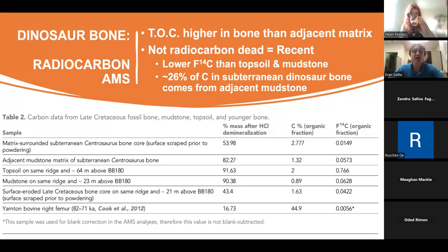And so we can look at this further through radiocarbon accelerator mass spectrometry. And what we see is that the total organic content of the dinosaur bone is higher than the surrounding matrix. And so there's an enrichment of organic carbon in the bone. Now, the radiocarbon in that is not dead, so it's relatively recent, again, consistent with what we're seeing in the amino acids. However, the F14C is lower in the bone than in the topsoil or the mudstone.